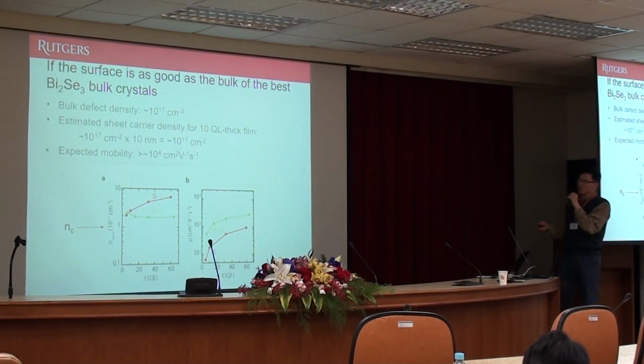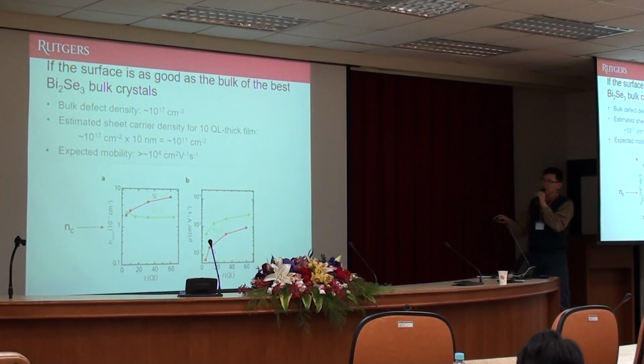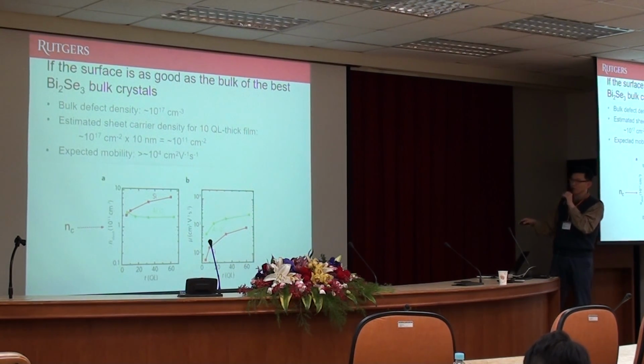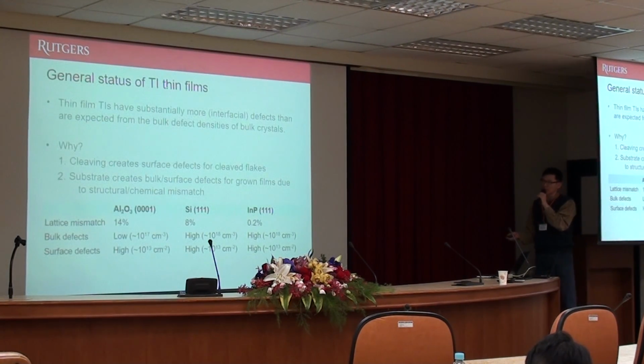But imagine if you can lower the surface defect density, if your surface defect density is similar to the bulk defect density, let's see if that is possible, then in principle you can achieve quite low, something like 10 to the 11 per square centimeter, even for something like a 10 nanometer thick film. So if you can suppress the surface defect density to the level of bulk, then your total carrier density could be way, way lower. So basically, the surface defect density is really currently dominating.